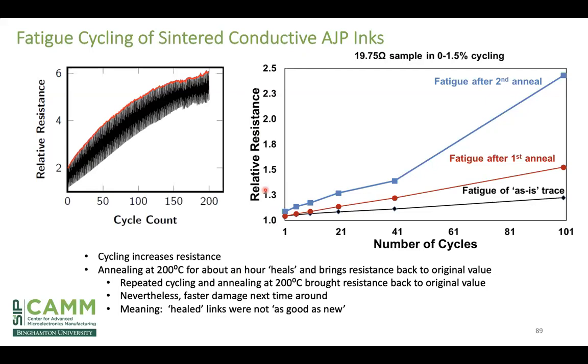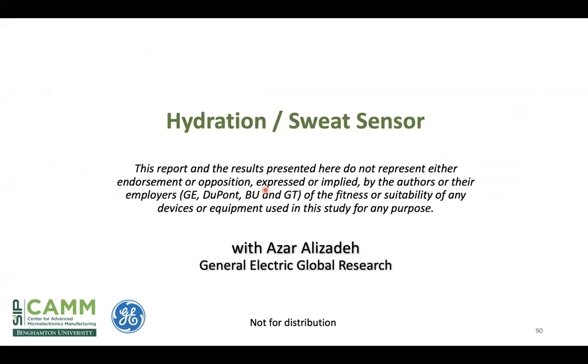So it may be still good enough for many designs, which are quite tolerant. But keep in mind that bending of any nanosilver ink formulation is in fact doing damage. It's causing cracks to the individual interfaces between the particles. And some can be annealed as the substrate and the viscoelastic properties recover. But damage done is damage and will in fact impact the resistance over the long term. And so it's good news that we healed, but not quite as good as new for the future. And so a good point to keep in mind as we design for these application spaces.